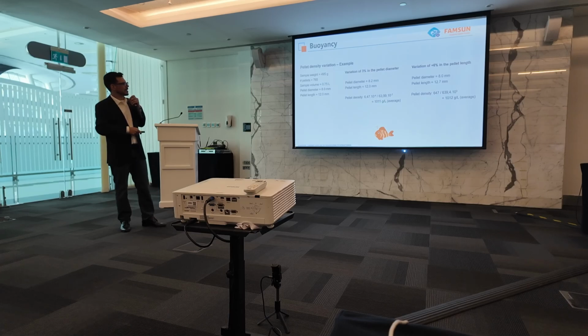So let's imagine we have a variation of 3% in the pellet diameter. Now our diameter is not 8 anymore, it's 8.2 with 3%. And now I calculate a new pellet density of 1,011. This should still sink in the fresh water, but float in the salted water because now we have a smaller density than the density of the salted water.